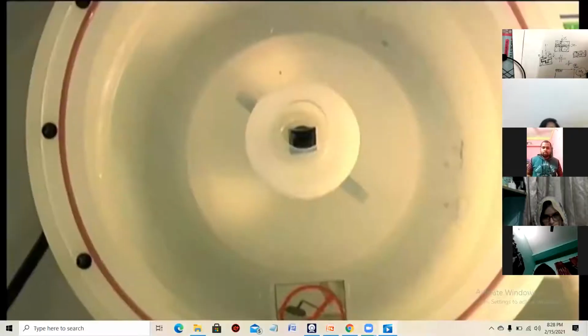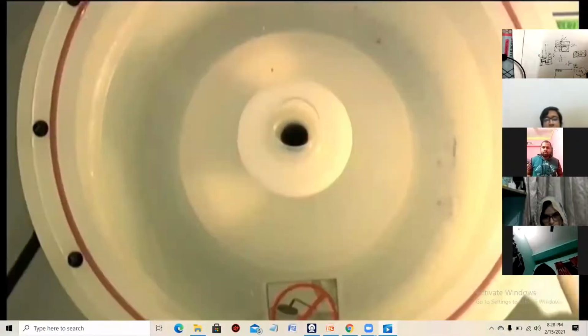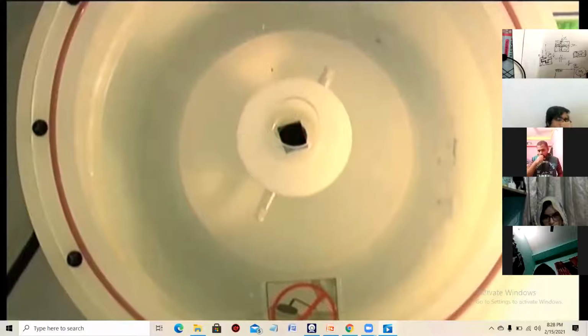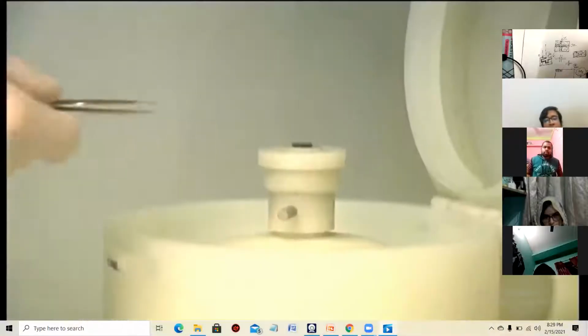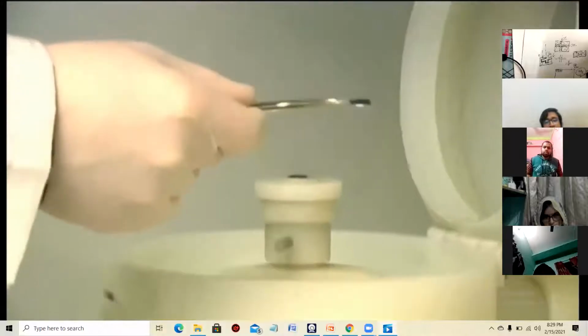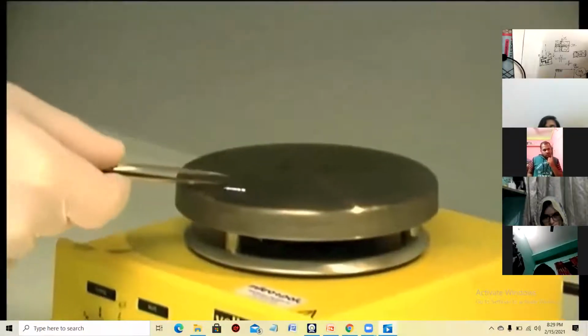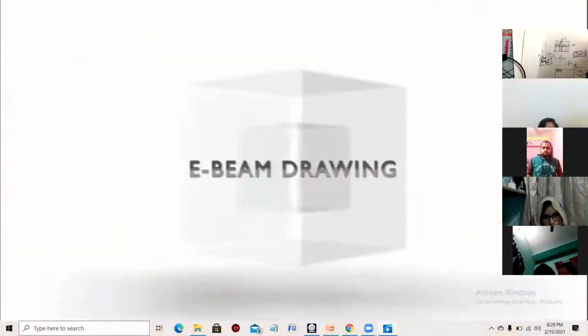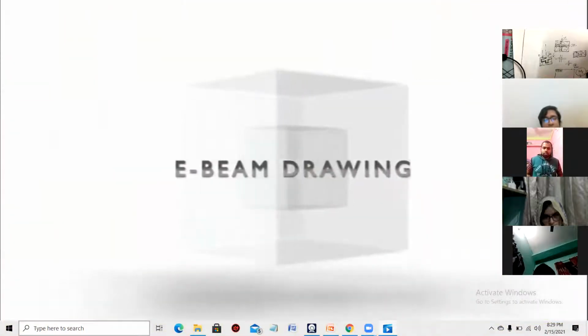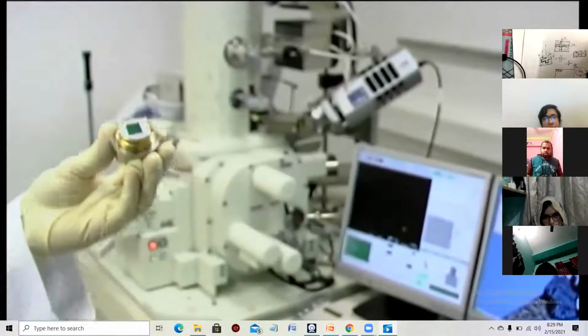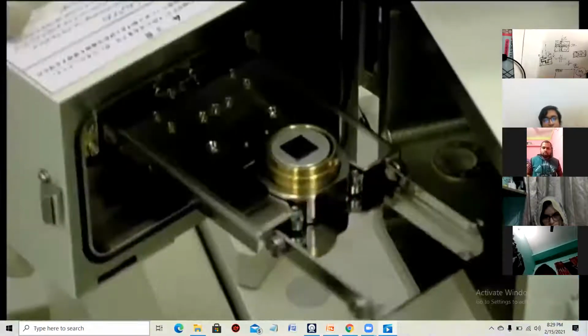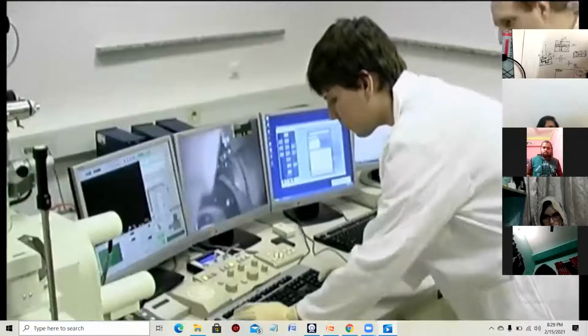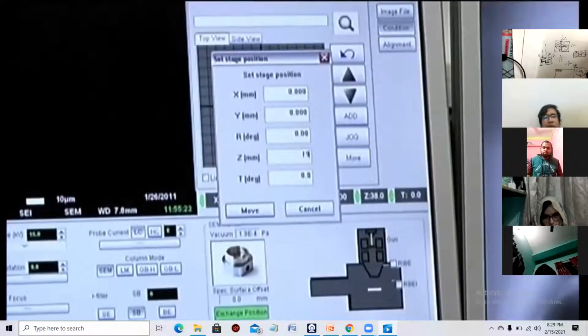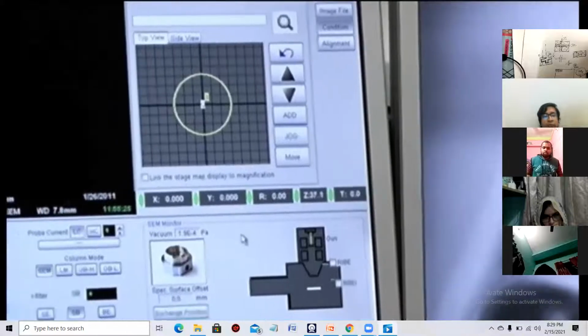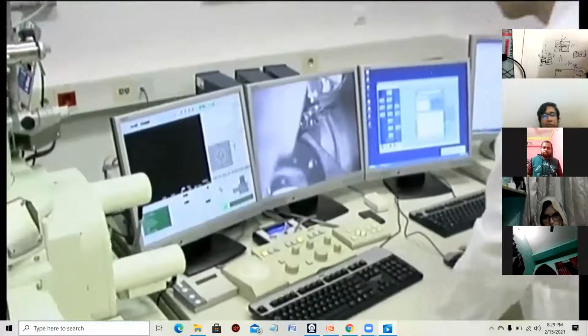With the use of a spinner, a uniform thin coating of a few hundred nanometers thickness can be deposited over the silicon. The polymer is then hardened by baking it at 200 degrees centigrade. When the wafer is prepared, it is inserted into the electron microscope, where the circuit is drawn. The electron beam precisely follows the design of the circuit and only irradiates the previously defined parts of the wafer, where the electrodes will be.